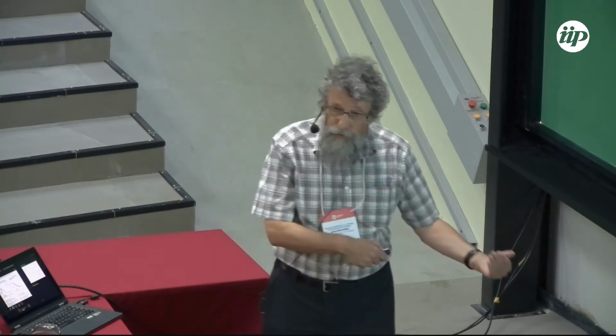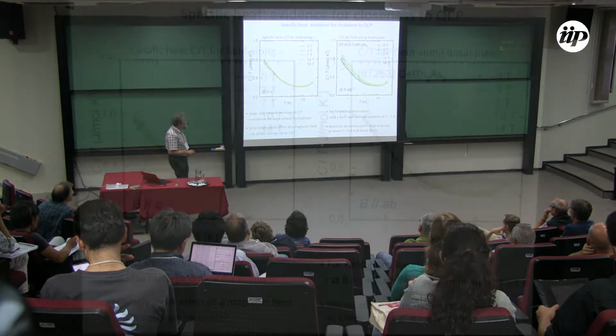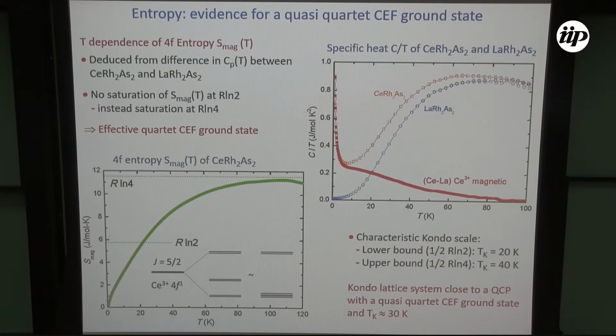And just looking at lower field, it seems that this transition emerges from lower temperature upon increasing the magnetic field, so that there is something at lower temperature. But we found something more interesting also at lower temperature, namely what we traditionally do. We look at the 4f specific heat up to very high temperature, so measuring the cerium sample and measuring the lanthanum sample, where there is no f electron, making the difference. That is C/T. You integrate, you get the entropy as a function of the temperature.